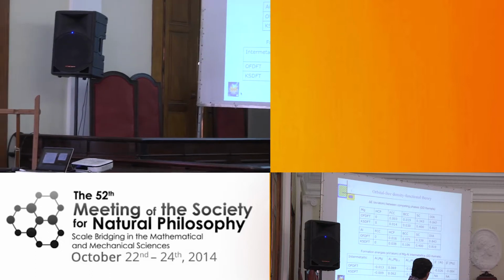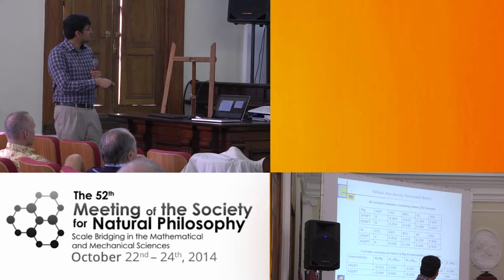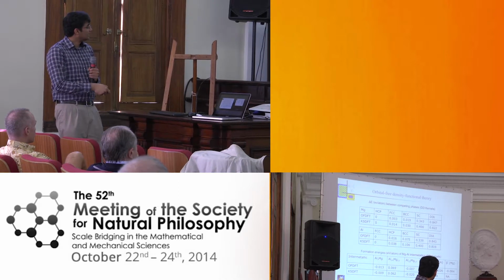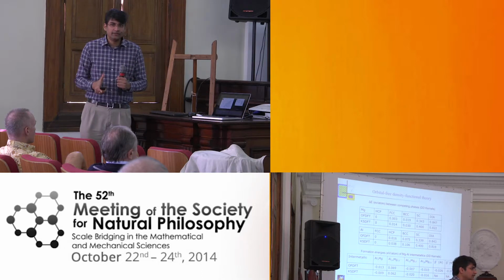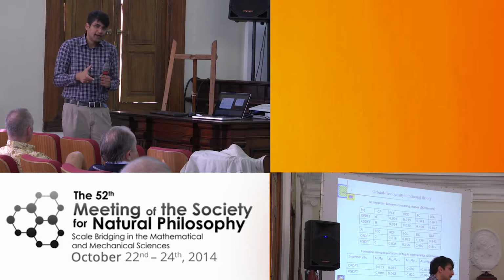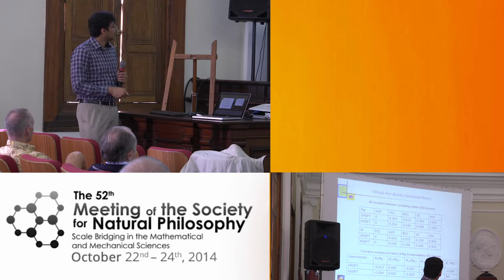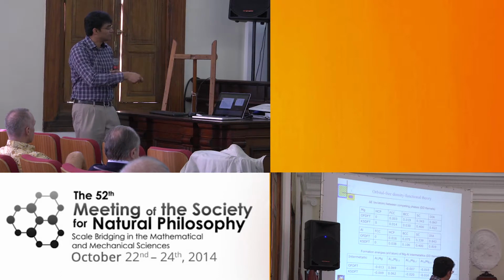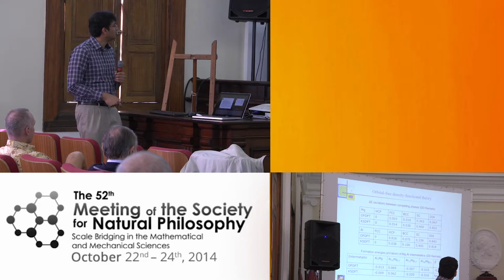And then we also computed the formation energies of aluminum magnesium intermetallics. And as you can see, again, the results are in good agreement with Kohn-Sham DFT. These beta prime phases of aluminum and magnesium involve pretty huge unit cells. These have about 800 to 900 atoms in a single unit cell. They have a long range order, but there is no short range order in these phases. And so we were not able to do Kohn-Sham DFT calculations, but we could get to these system sizes using orbital free DFT calculations, because orbital free DFT is less expensive than Kohn-Sham DFT.